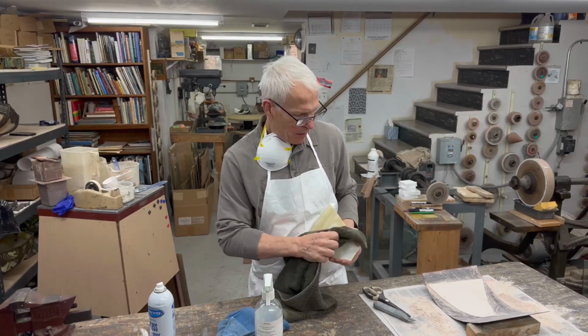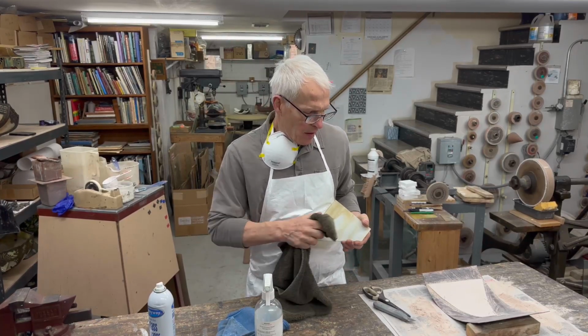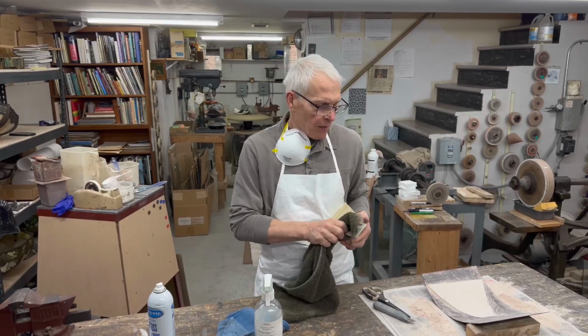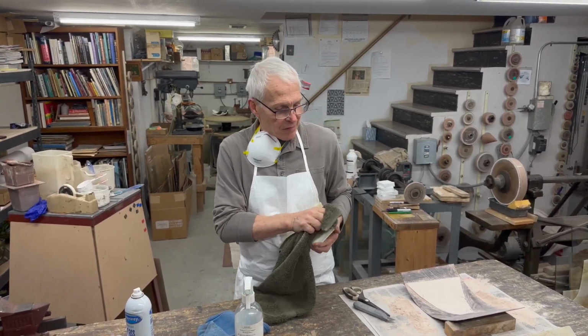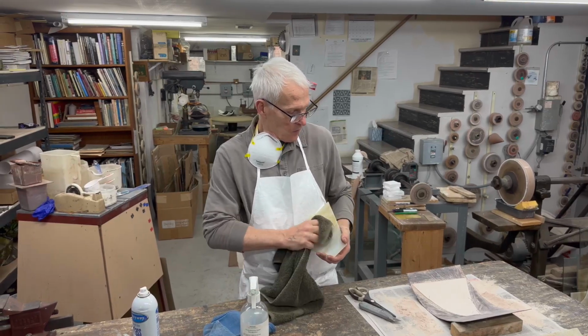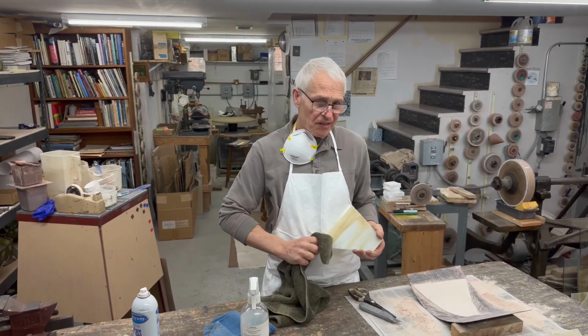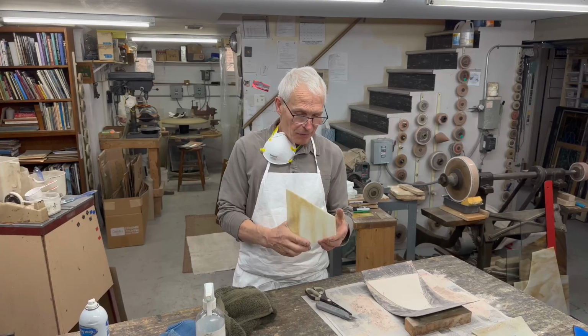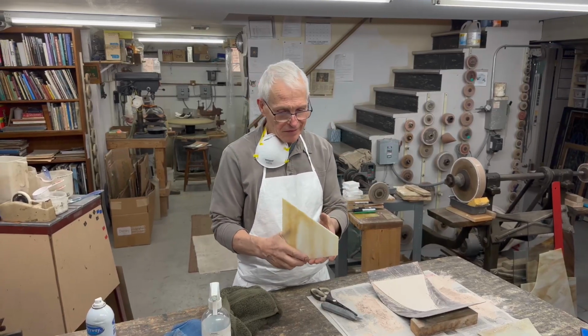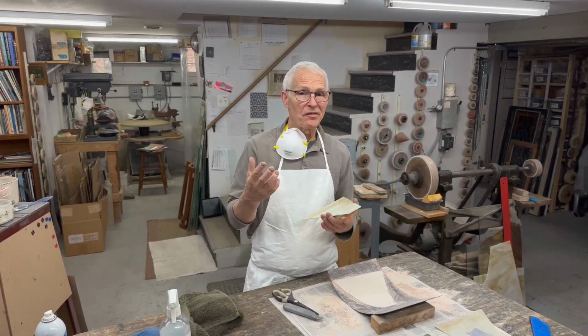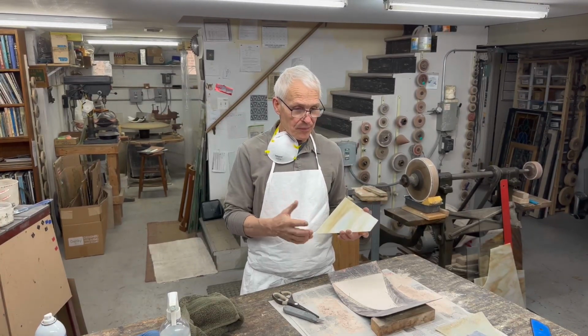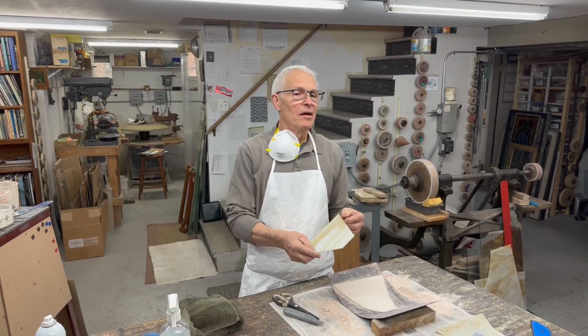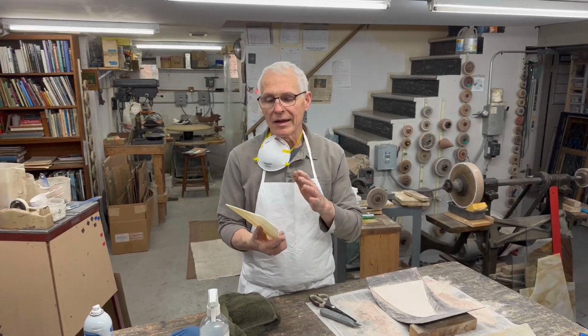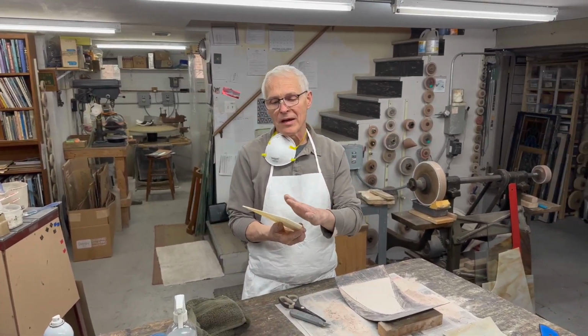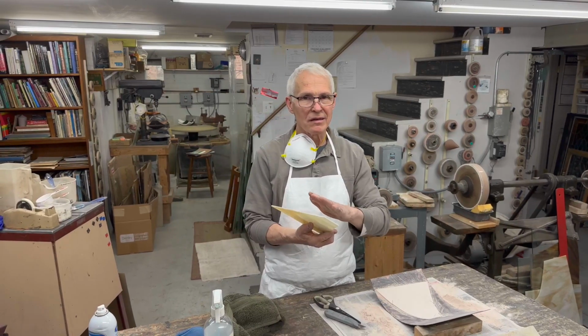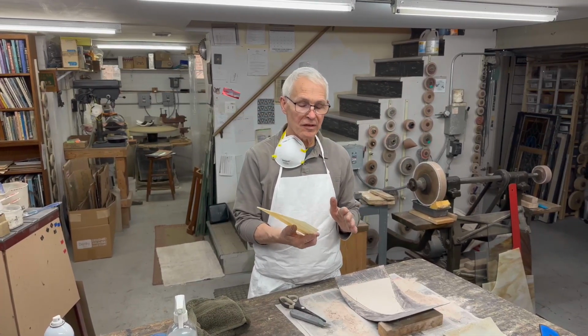One thing you'll want to avoid is using some glass, like antique glass that's probably 80 or 100 years old, because if you use old glass, for whatever reason, it devitrifies in the kiln. You'll end up going through all this work firing the glass and taking it out, and it'll all be devitrified, which means it's going to be all chalky, scummy, and sandy on the surface.